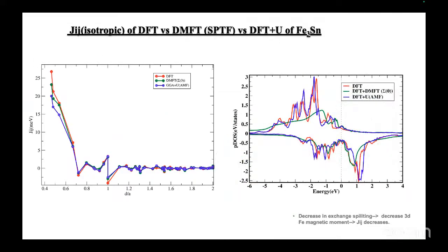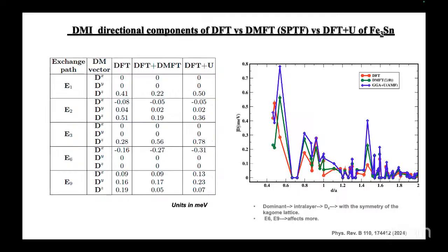So then we further analyze the effect of the correlation on my JIJs. What we observed as we look at the density of states plot for the three cases is that the decrease of the exchange splitting can be seen in the structure, which reflects the decrease in the magnetic moments. And so we saw the decrease in the JIJ exchange strength, and quantitative changes can be seen in the first nearest and the second nearest interactions. So we see a slight decrease in the coupling strength as we go from DFT to DMFT plus DFT plus U. And looking further to the SOC part, which is quite interesting when we see...